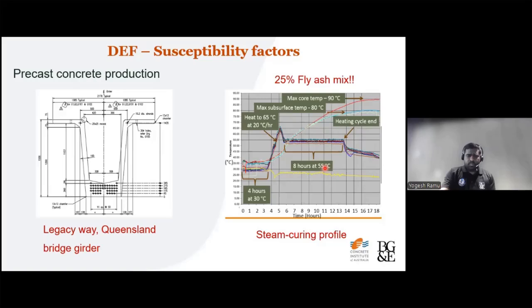So DEF can very much be a possibility here, but with the temperature alone we cannot say correctly. We have to analyze all the other factors like cement binder chemistry and exposure, everything we have to consider to arrive at the conclusion whether it's going to be an expansive DEF, or just DEF sitting in the concrete that doesn't do anything to the concrete.